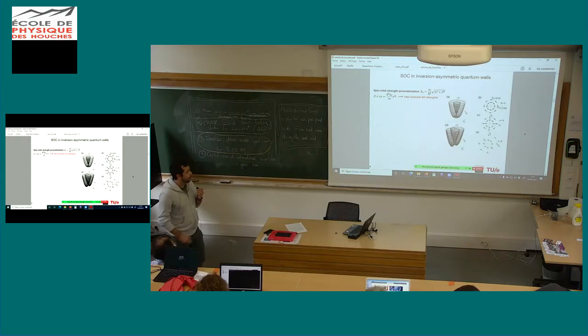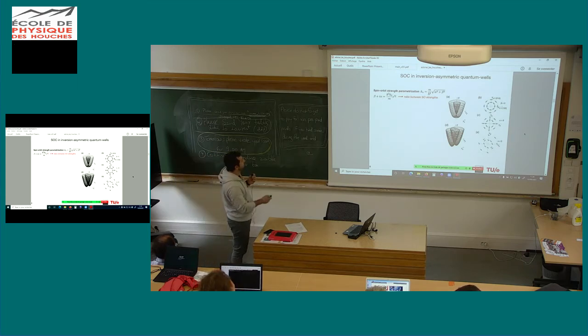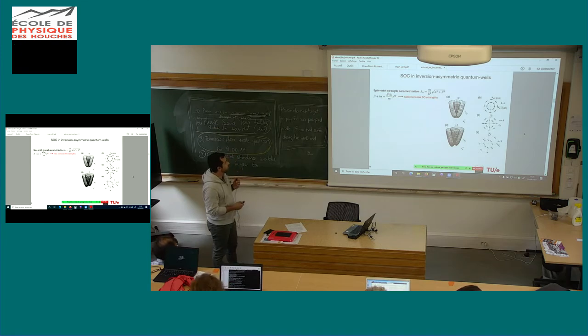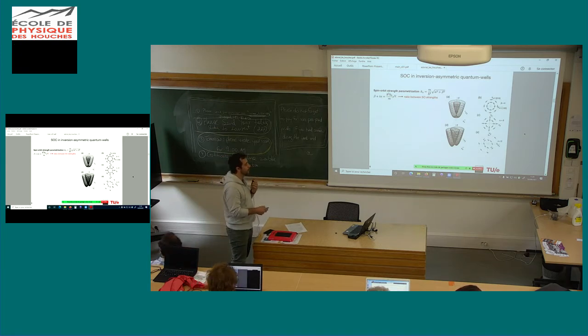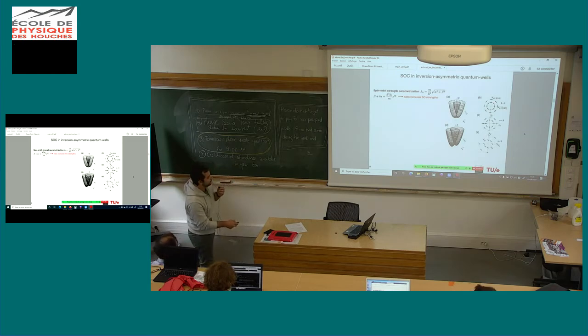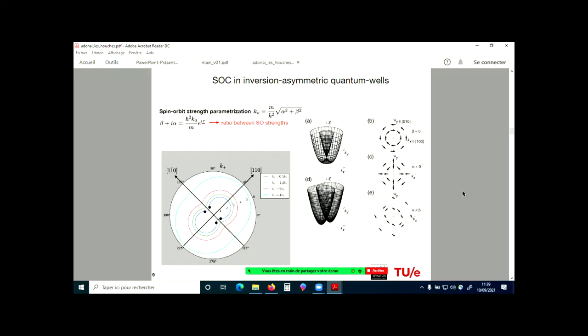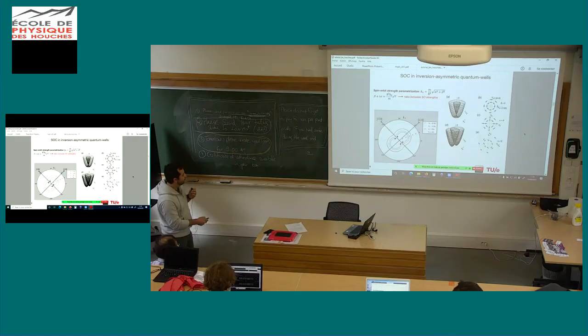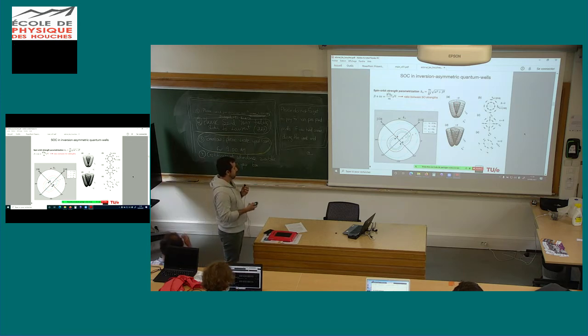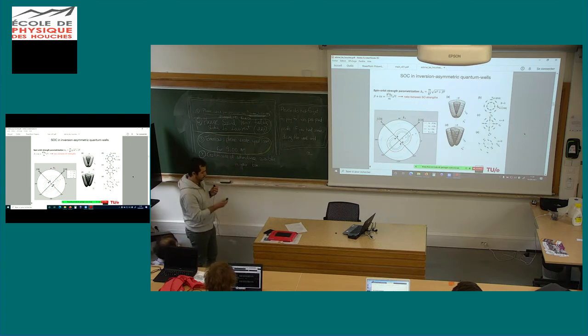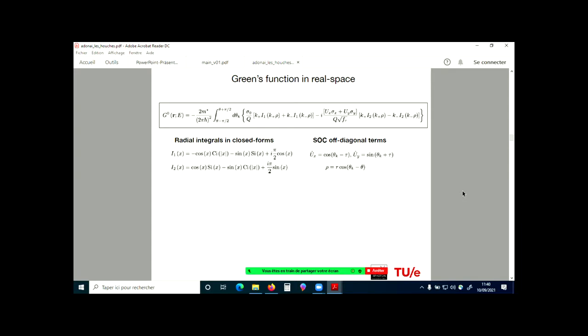The interesting thing here is the interplay between these two terms. Alpha is Rashba and beta is Dresselhaus. On the right, you can see the dispersion energy, and the arrows correspond to the spin direction. You can see that it's isotropic when we have just one of these terms, alpha or beta. It becomes interesting when there are both terms, alpha and beta. In this case, the Fermi contour becomes curved, and this curvature has a very strong impact on the real space properties of the electrons. One way to see that is by calculating the Green's functions and the local density of states. I'm just going to skip a little bit.